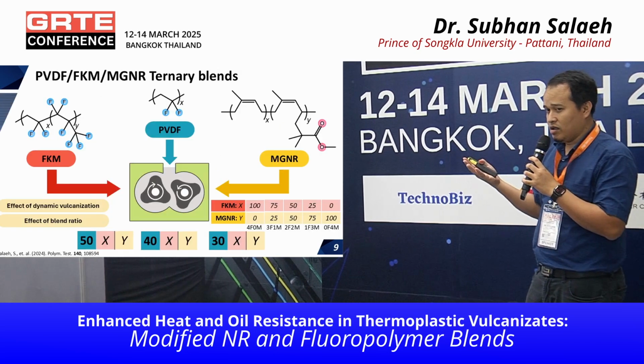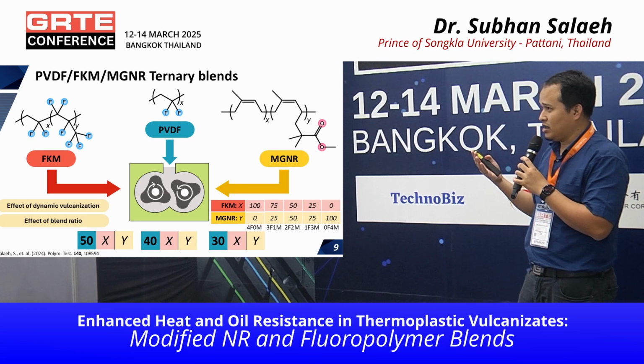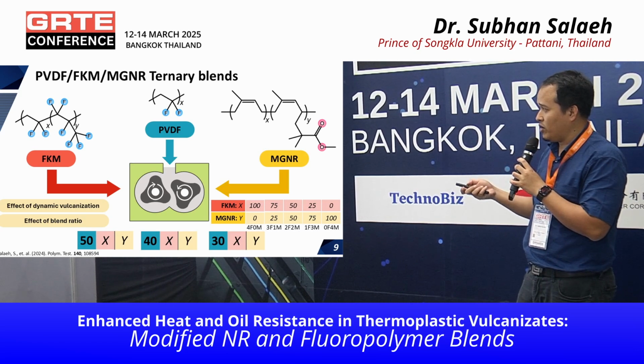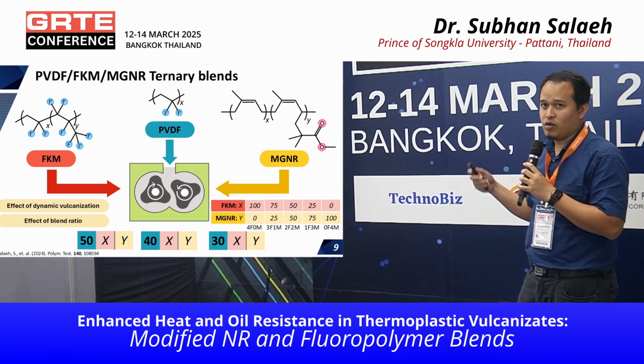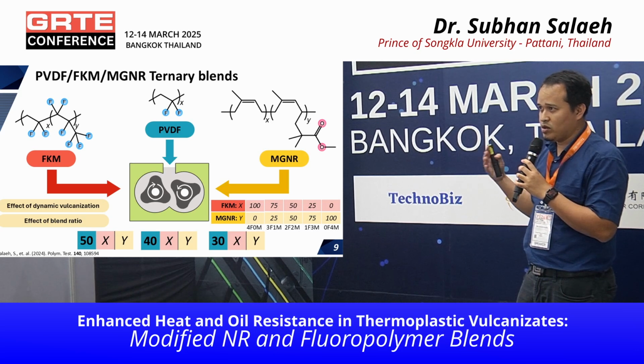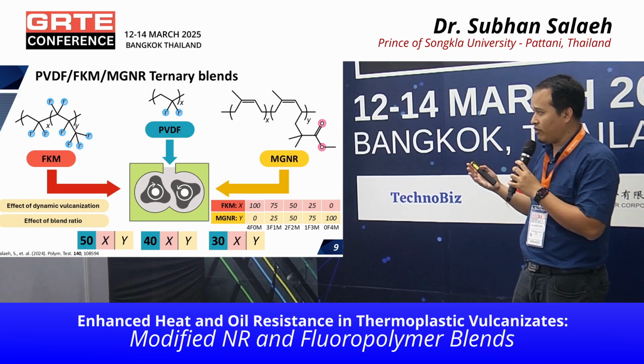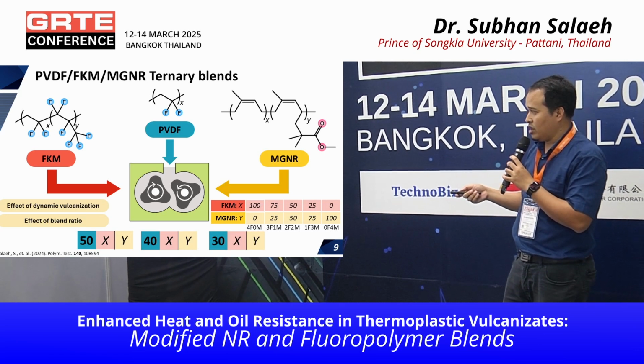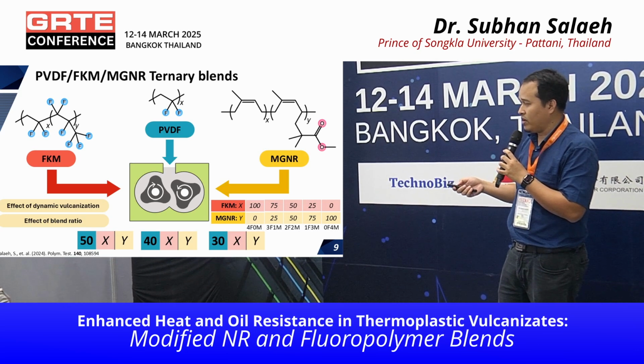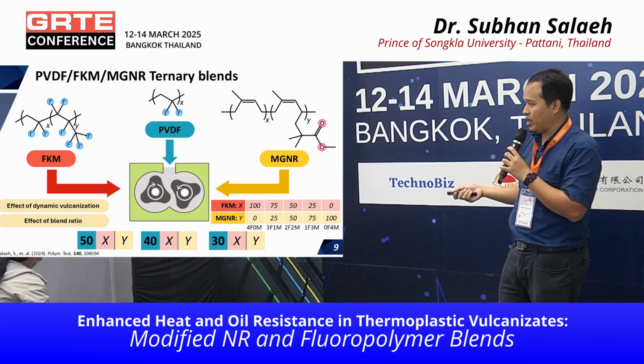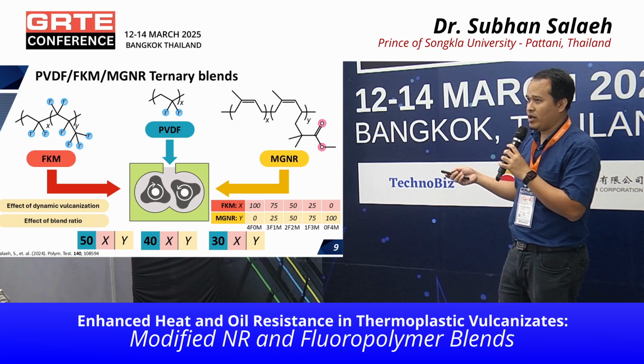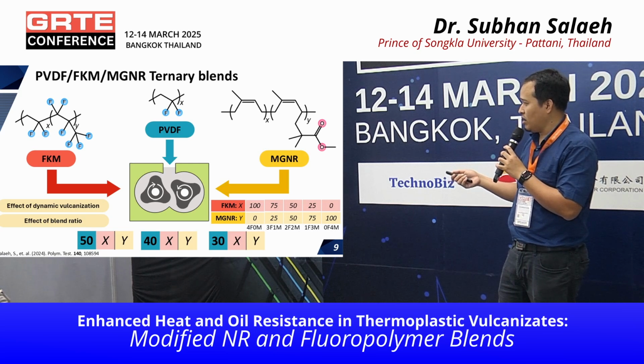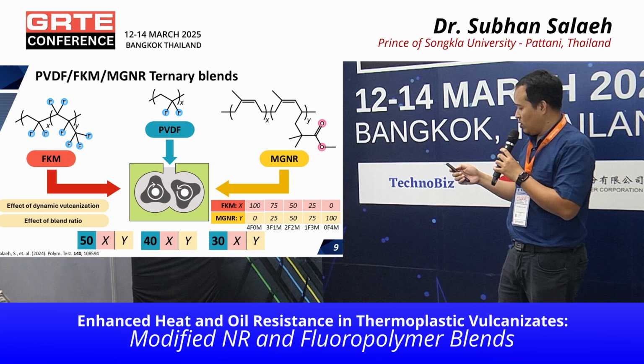Therefore, in another work last year, we prepared a ternary blend by adding FKM. We add FKM because we want to increase the heat and oil resistance of the TPV. We studied the effect of dynamic vulcanization and blend ratio, varying the amount of PVDF at 50, 40, and 30, and also varying the ratio of FKM and MGNR from 100:0, 75:25, 50:50, 25:75, and 0:100.